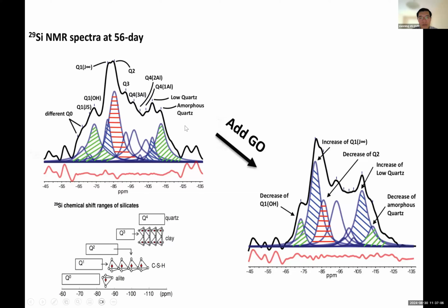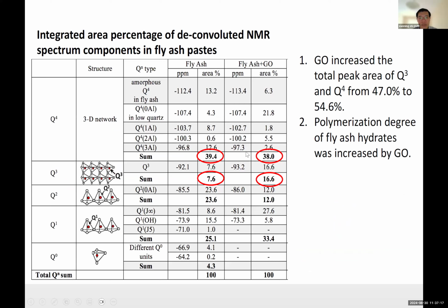But this is a very busy chart, and the main storyline is that with a trace amount of graphene oxide, you actually change the hydration products and make them quite different. The numerical numbers are here. Again, the total peak area under Q3, Q4 is increased from 47% to almost 55%. So in other words, this indicates an increase in the polymerization degree. And this kind of network structure, or higher degree of polymerization of the inorganic material, translates to better resistance to chemical attack, such as resistance to deicers or sulfate attack or acid attack.